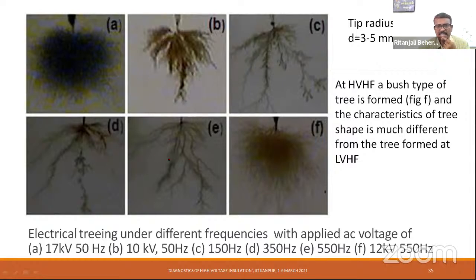The next C, D, E, all these are stressed at 10 kV at different frequencies, in increasing order: C is at 150, D at 350, and E is at 550. So when the frequency is higher, they become more branchy, more fibrillar in type. And the last one, F: the difference between E and F is that both are at the same frequency, but E is at 10 kV and F is at 12 kV. That means at a slightly higher voltage of the same high frequency, this becomes mostly a bush-branch type of tree. So that is the effect of high frequency combined with high voltage.